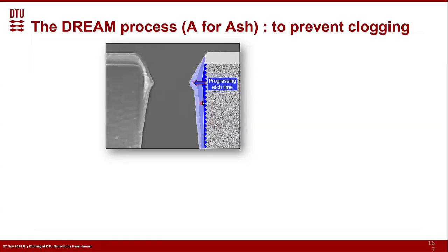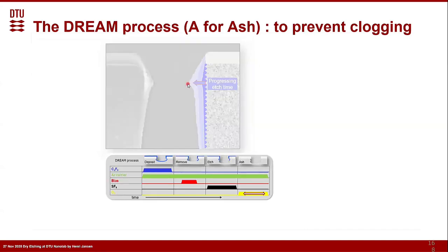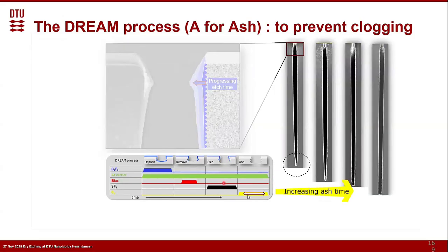But what you can also do is, when you see that, yes, we know that the thickness at the top side is starting to grow a thicker and thicker layer, which starts to close the trench. The best thing now to do is let's try to see after having done the final etch. What we do, we etch away all the fluorocarbon. So we take an extra step. It's called the dream process.